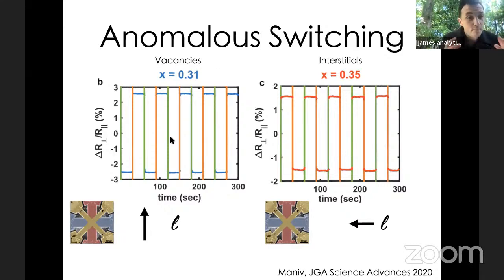Let me emphasize how bizarre that is. There's already a lot of bizarre properties, but let me emphasize how important that is, because if the magnetic order, the Néel order, is basically the same, you wouldn't have expected it to be any different between one intercalation and the other, given it's really just disorder that is changing, at least in principle. You'd expect the same kind of spin polarized current to rotate the Néel vector in exactly the same way. But what this would be saying is that for the same geometry, the only thing that's changed is the disorder. The Néel vector is actually being rotated oppositely for the systems with different intercalations. And this is where the determination of the magnetic order became super important.